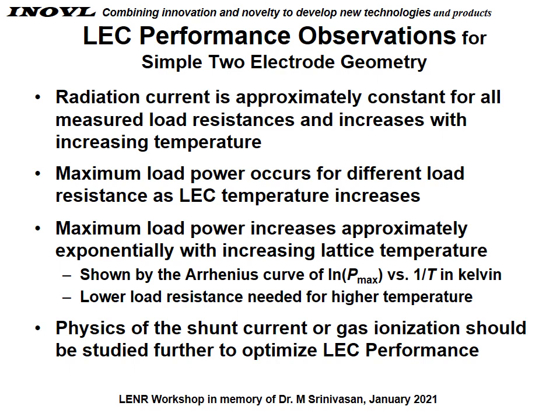Some observations. The radiation current is approximately constant for measured load resistances and increases with increasing temperature. Maximum load power occurs for different load resistance as temperature increases. Maximum load power increases approximately exponentially with increasing lattice temperature, as shown by the Arrhenius curve, and the lower load resistance needed for higher temperature. The physics of the shunt current or gas ionization should be studied as an opportunity to optimize the LEC's performance.